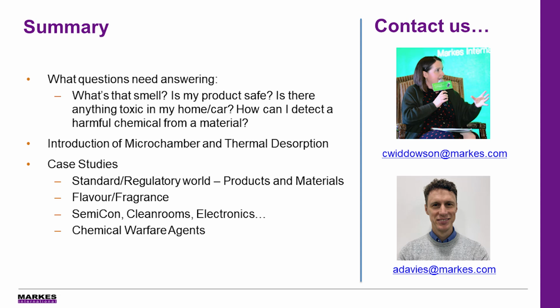Now, if you are looking for something that is not emitted at room temperature onto a sorbent tube, a really good method is ASTM D7706, which is a guide about how to use the microchamber for material testing. And in there, it talks you through the incremental increase of temperatures so that you can identify the profile of your material over a range of different temperatures. So for example, if you're looking for a specific compound that you don't want to be released from your product, or an odorous compound that you're concerned about, then you can do these different types of analysis.